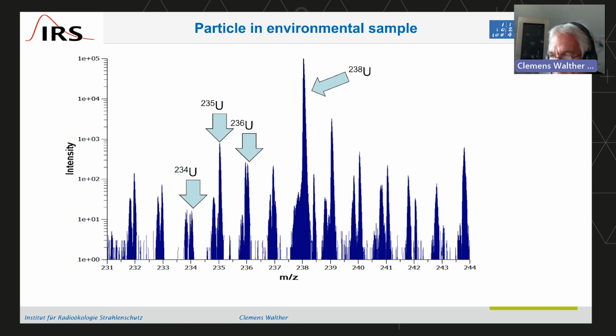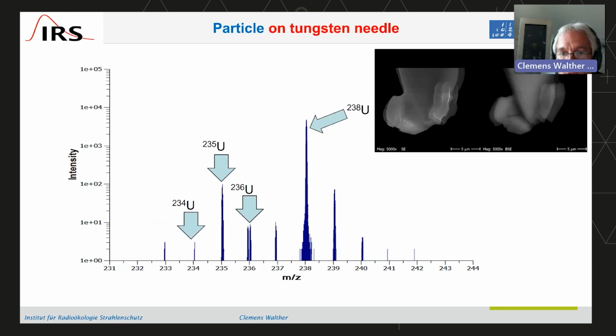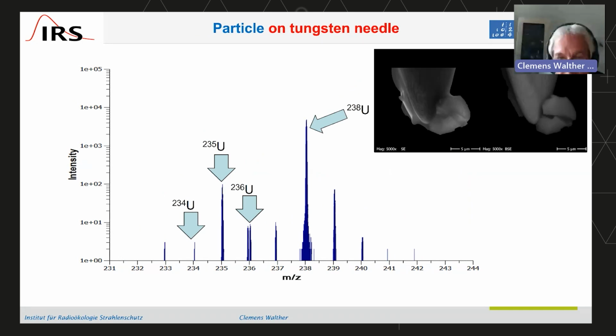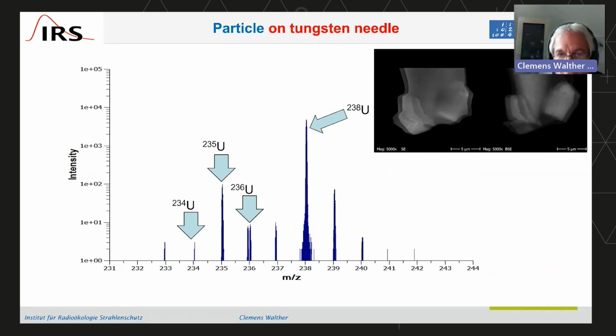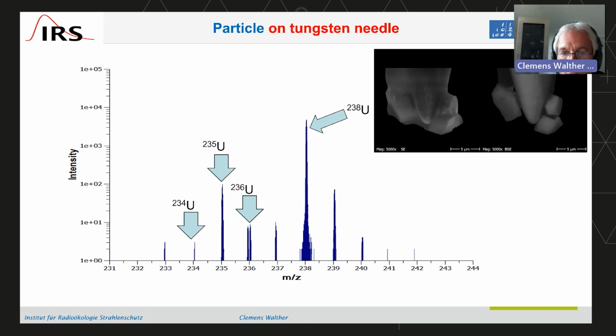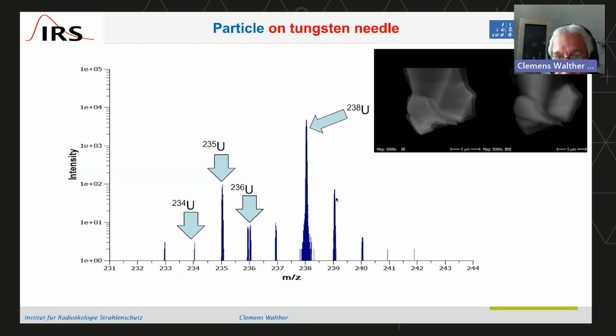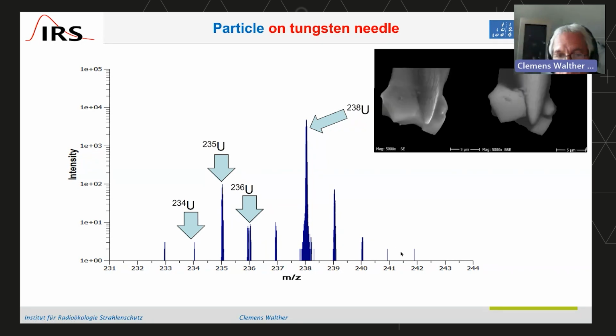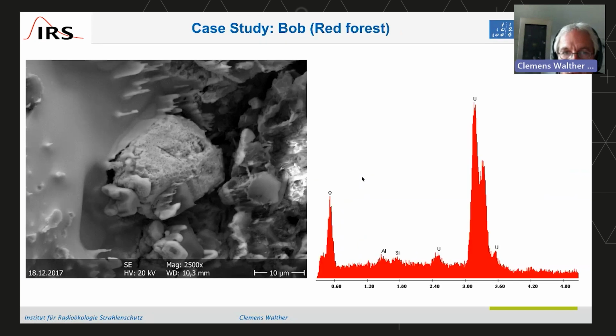So that tungsten tip also gives you good background suppression, because if you compare this one, this is an unprepared environmental sample in our mass spectrometry picture. You can see the uranium, but you can see all kinds of additional peaks. And if you look at the same picture when the particle is mounted on the needle, then you see that most of the background is gone, and you see the uranium isotopes remaining. And here you have either uranium hydride or you have plutonium. You cannot decide at this time. You can decide later.